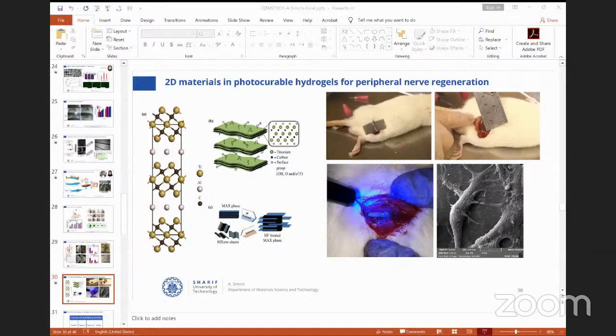The other topic where nanomaterials are used is nerve regeneration. As you know, nerve regeneration is a hot topic now. The problem is that for nerve regeneration, we should have a conductive material. Nerves need a conductive material. Most polymers, almost all polymers, are not conductive. Therefore, we try to use two-dimensional materials. The best one is MXene, which has a high conductivity. We developed a procedure to have a special type of MXene based on titanium, carbon, and so on, a very conductive material. We added MXene to our hydrogel and use it for